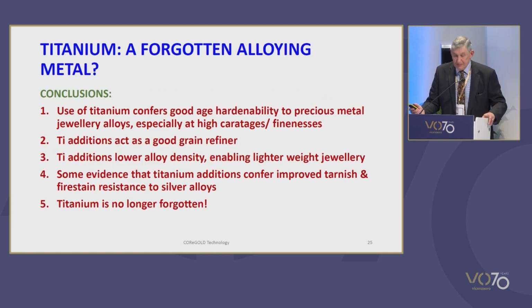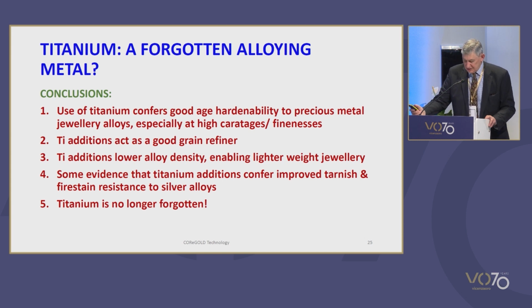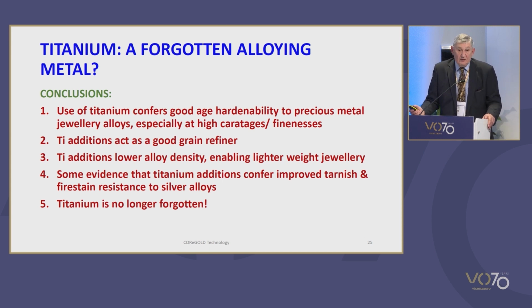The use of titanium in precious metal alloys confers good age hardenability to precious metal alloys, particularly at high caratages and finenesses. Titanium additions also act as a grain refiner in precious metal alloys. It also lowers alloy density, thus enabling lighter weight jewellery with economic benefit. And there is some evidence that titanium confers improved tarnish and fire stain resistance to silver alloys. So, final conclusion, titanium is no longer forgotten.